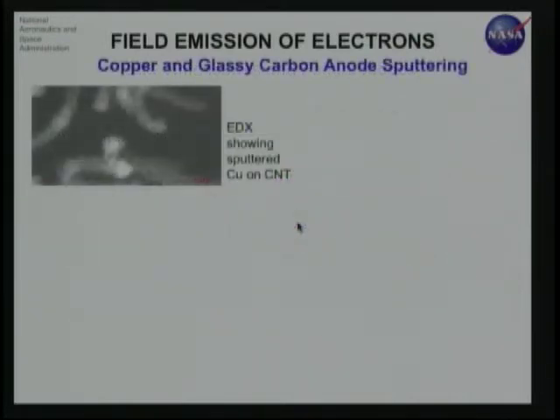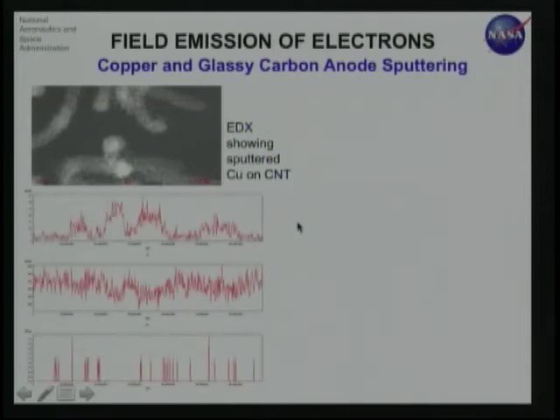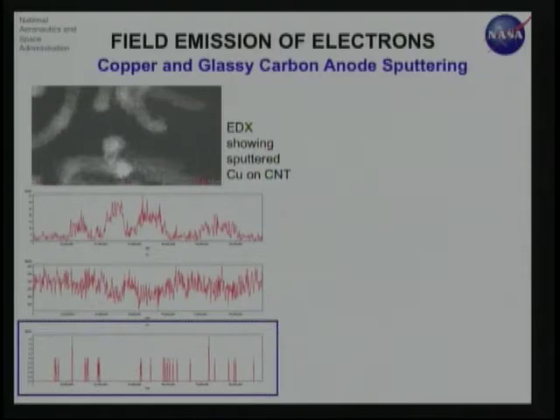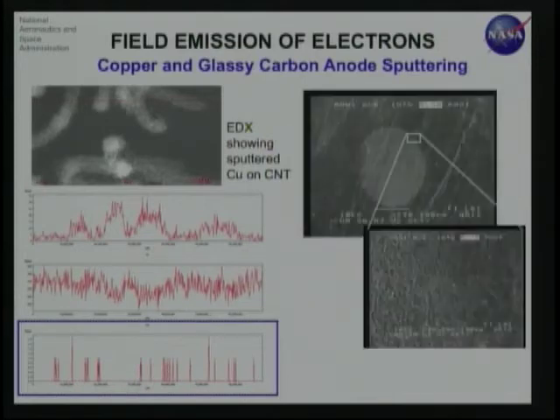And that can be seen more clearly, this is an EDX that shows you that we do see that when you use anodes like copper and glassy carbon, you do have sputtered material that falls on the emitter itself and masks the surface. It's the same thing here. You can see that the circular region of the emitter surface is completely discolored, and it's roughened out. And that's one of the reasons why you have a gradual failure.